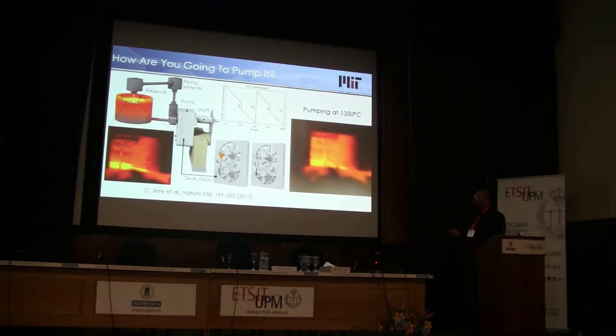Our initial pump was actually made out of an aluminum nitride composite. We're now interested in making pumps that are just all graphite, but no real intrinsic issue here. Our new step forward in doing all of this was these joints. In order to make a system like this with flowing liquid metal, you can't really make it out of all one piece of graphite, so you've got to connect pieces, and it's the connections where the liquid will want to leak. You've got to seal them, and so that's really our big contribution here, is figuring out how to actually seal against the liquid at these extreme temperatures, and the seals are all refractory and do not chemically interact with the liquid we're pumping as well.